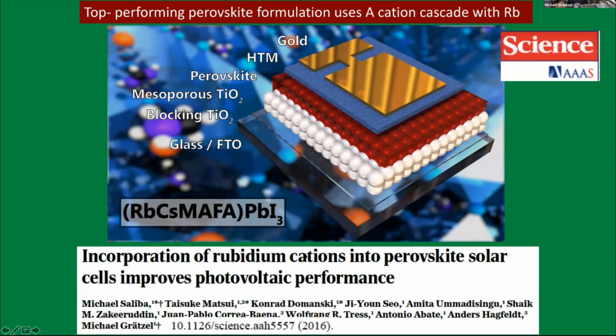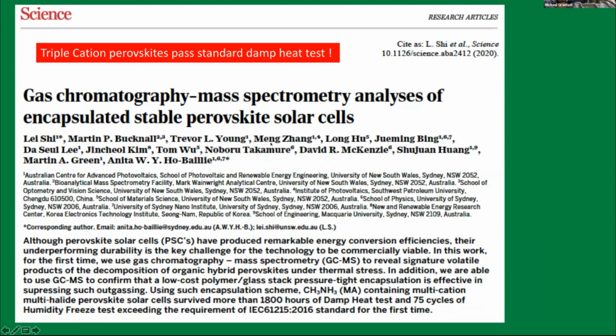Okay, so if I now fast forward to science 2020, here you see the experiments from the Australian group I mentioned, and they passed this famous damp heat test and humidity freeze test. These are tough tests. For example, the damp heat test is usually 1,000 hours, 85 degrees, 85% humidity. It's like when you go in your sauna and you turn the temperature to 85 and humidity 85, and you stay in there for a month. How much would be left of your skin?